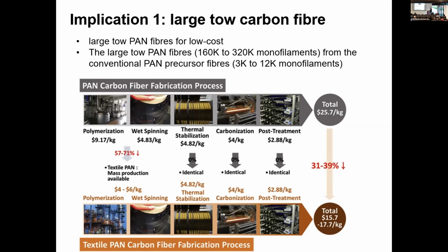So the first is the carbon fiber. We have to create cheap carbon fiber to be accepted by the industry. And so comes the large tow carbon fibers. With large tow carbon fiber, the efficiency increases, and particularly in the polymerization stage, you can reduce the cost by 70%. And for the whole process, you can reduce the cost by 40%. So particularly for non-aerospace applications, we come with these large tow carbon fibers.